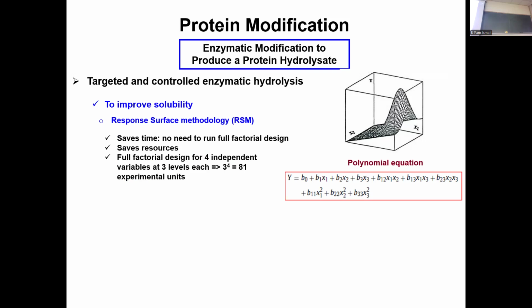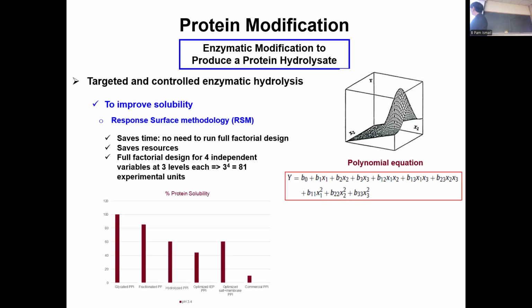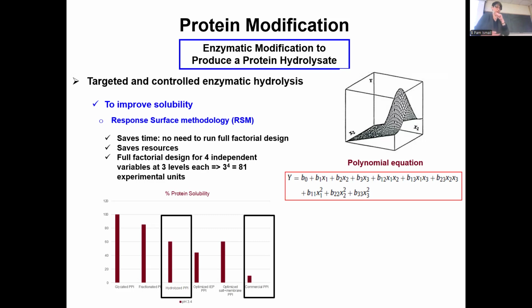And here's an example of 4 independent variables, 3 levels. You have to have 81 experimental units, whereas if you do RSM, you do 24 in this case. We did that hydrolyzing pea protein, and we took a commercial PPI as a starting material, and it was like 10% soluble, very pathetic. We increased it by 6-fold following the response surface methodology design.